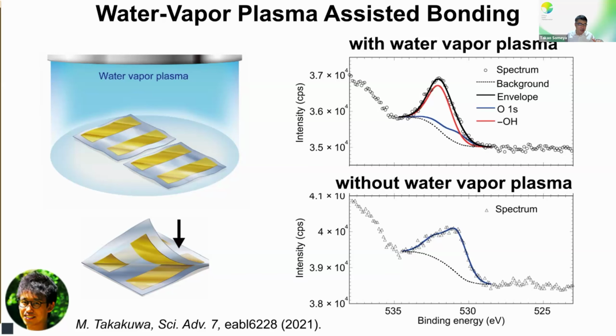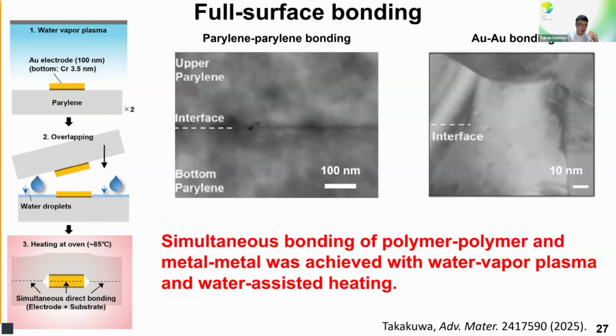So gold film is deposited on 1 micron thick parylene and exposed to the water vapor plasma to introduce OH groups on the surface, and then laminated together. And then eventually we realize the gold could be bonded, and also parylene could be bonded. We don't see any vacancy, and we get a tight connection. So in that way, we succeeded in laminating ultra-thin film without adding any glue, to maintain the total thickness to be super thin.